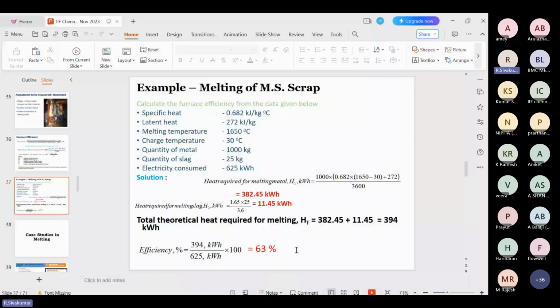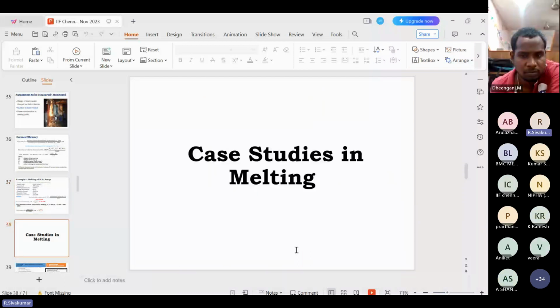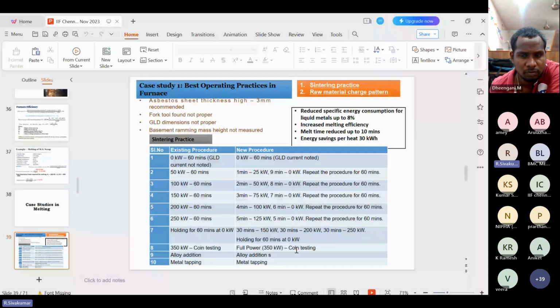Okay, sir. Here I shared some of the case studies in melting. In one of the foundries, we adopted the best operating practices in both the sintering and the raw material charging pattern. It led to reducing the specific energy consumption for the liquid metal by up to 8%, increasing the melting efficiency, and melt timing is also reduced by 8 to 10 minutes. Energy savings per heat is around 30 units.